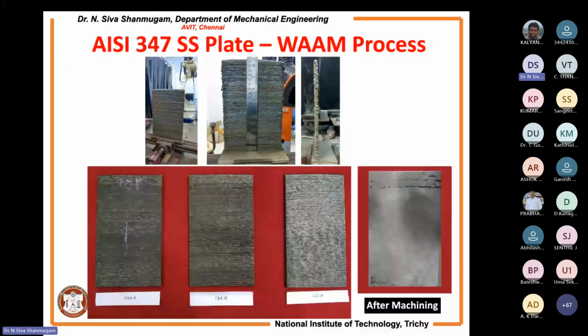We tried, we obtained the results, and the article has been published in the open forum. You can check during your free time. And also we are working with nuclear material, something like niobium, something like a 347 SS. We have created a wall. We have machined it to find out the buy-to-fly ratio. From that, we have extracted the sample for finding out the strength of the material.